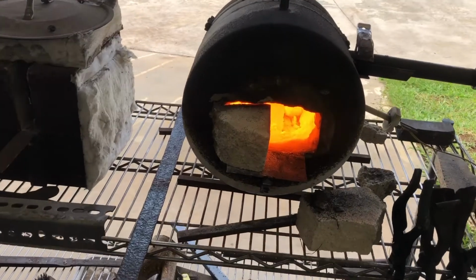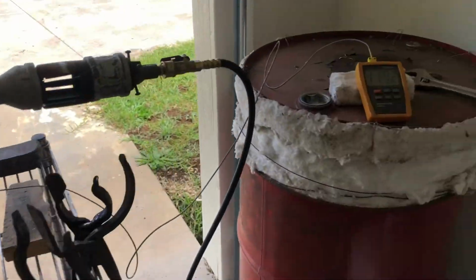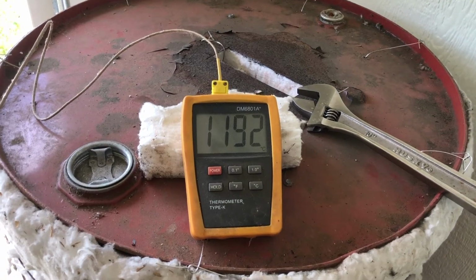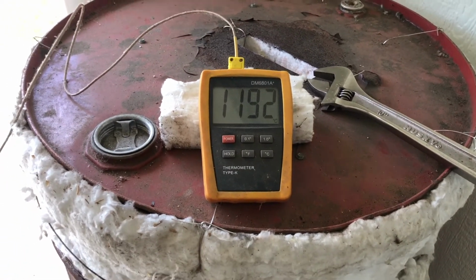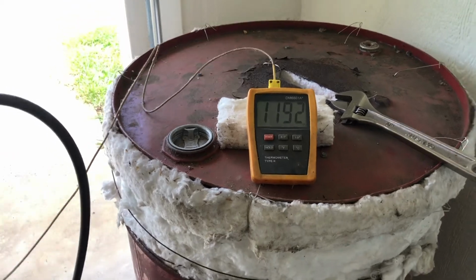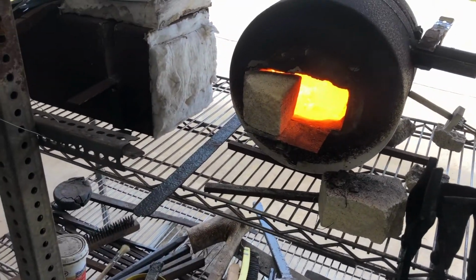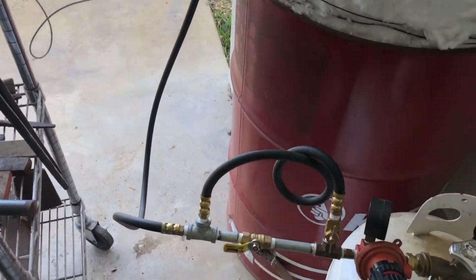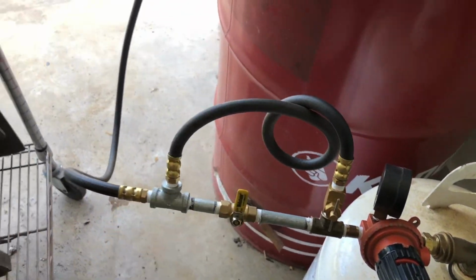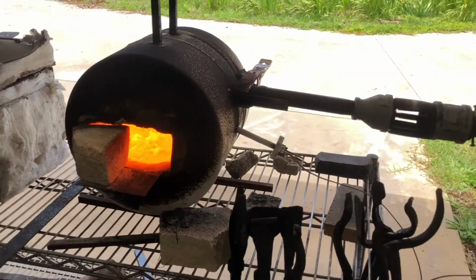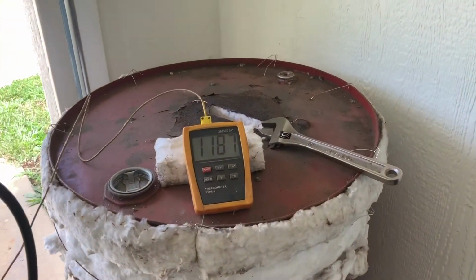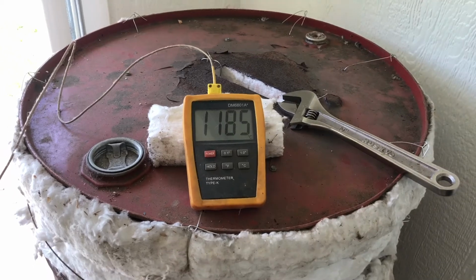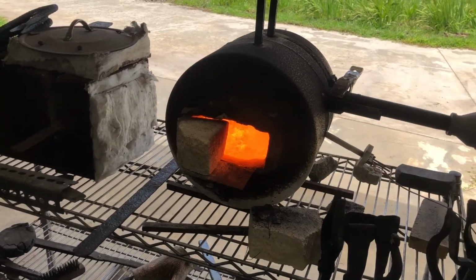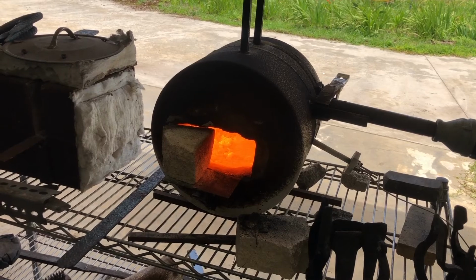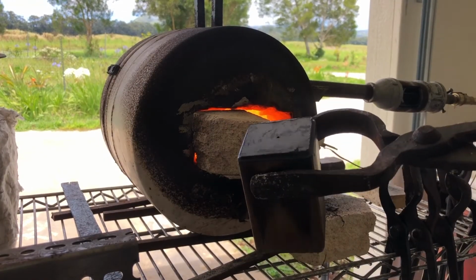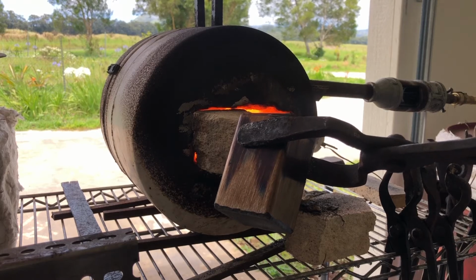So the forge is just about up to temperature now. We're at just under 1200 degrees Celsius, so just about 2200 degrees Fahrenheit. What I'm going to do before I go grab one of the canisters is I'm just going to put my forge on idle. It'll cool off a little bit in there. You can see it's dropping some. But this way, it's not quite as much of a shock to the canister when I set it in front of the forge.